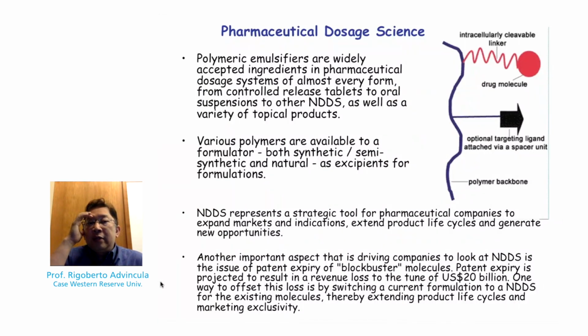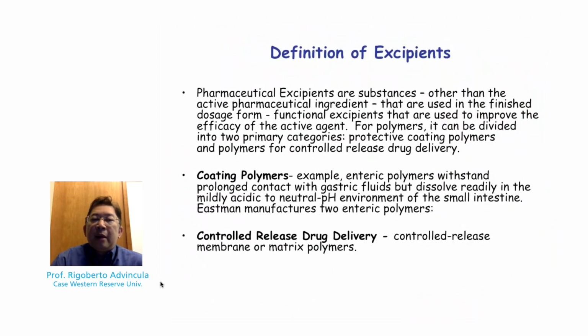So in a pharmaceutical dosage, what happens is that a polymer, for example, can be added to emulsify the whole composition, and this polymer emulsion or excipient is expected to provide some of this controlled release, quote-unquote, pharmacokinetic cycle. And this can be fulfilled either by synthetic or semi-synthetic or natural polymers even. The good news is natural polymers like cellulose or starch are actually quite abundant and used a lot in extending release or controlling a polymer function.